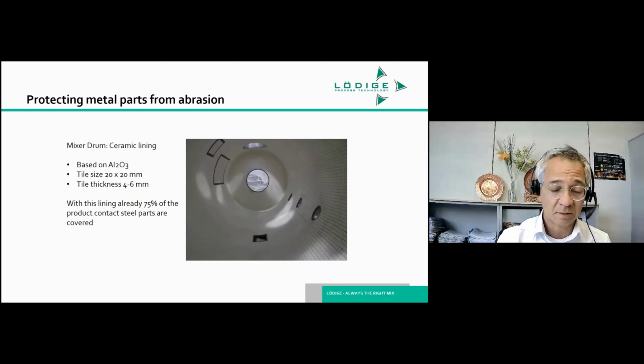And for the drum, it has been established over the years now, testing different methods of coating, that ceramic lining seems to be currently the best option. And the interior looks like bathroom tiles, small tiles which are cemented into place, and these small tiles allow you to follow the curvature of the mixing drum, because for different sizes you have different curvature of the mixing drum, so you have to adapt. And 20 millimeters side length seems to be ideal for this. And the material is cemented into place, giving a good fit.